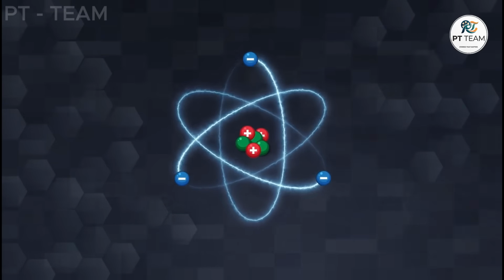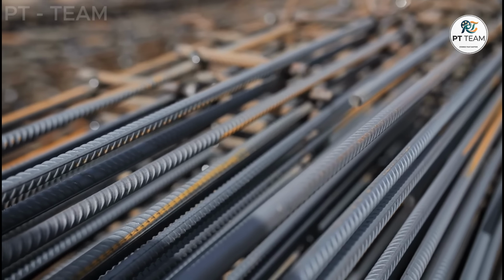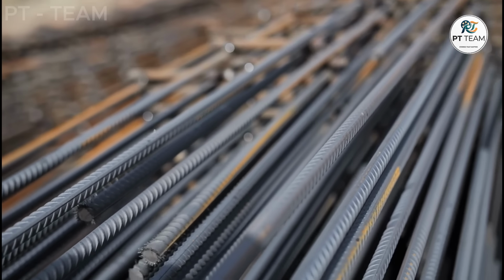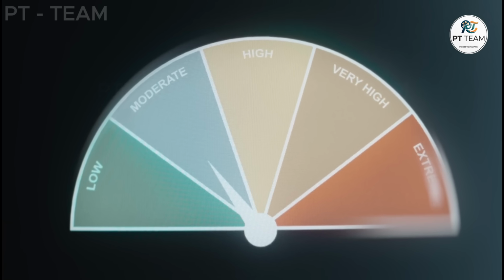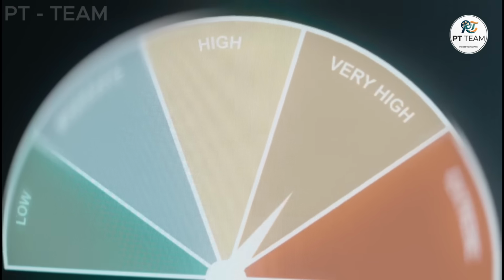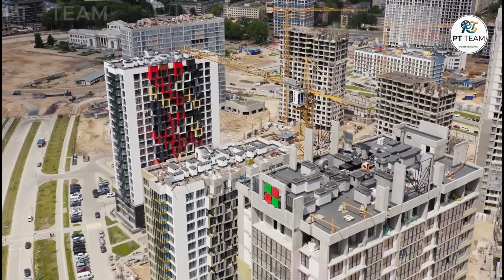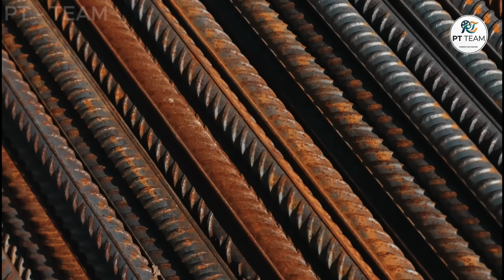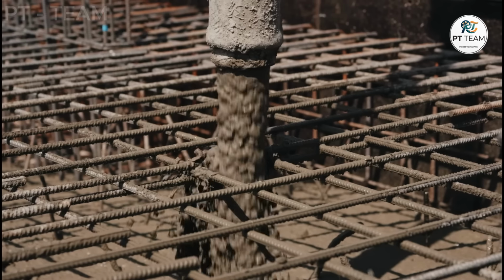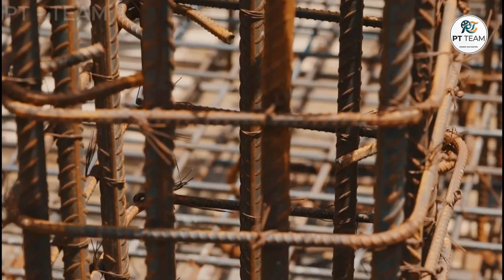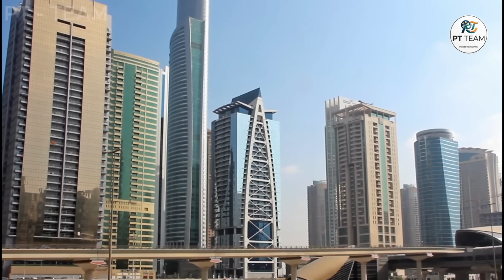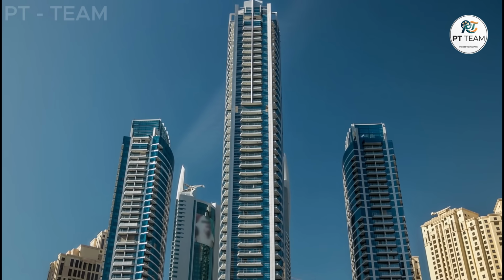But eventually, the concentration of chloride ions accumulating at the surface of the steel reaches a critical tipping point. Engineers refer to this as the chloride threshold. The moment this threshold is crossed, the highly alkaline environment is neutralized at the local level. The microscopic passivation layer is instantly destroyed. The chemical sanctuary is breached. The steel is now exposed and vulnerable in a dark, damp environment. This marks the end of the initiation phase and the beginning of the propagation phase. What happens next is a slow-motion mechanical disaster that completely changes the structural integrity of the building.